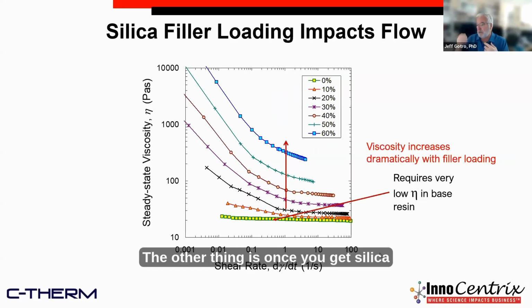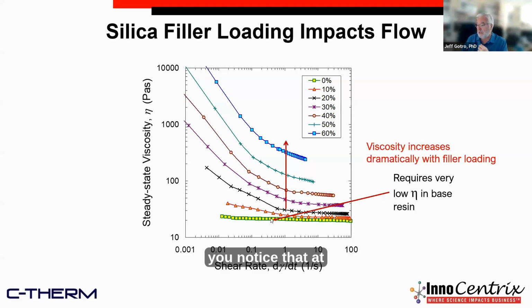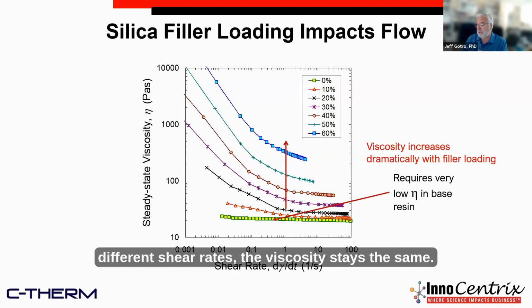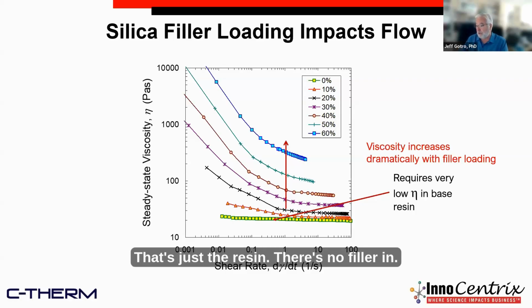The other thing is once you get silica filler in there, let's just say we'll use silica because that is the one that has the lowest, what I call, viscosity penalty. But when you load it up with various levels of silica filler, even then the viscosity goes up dramatically. In this case, the yellow curve at the bottom, you notice that at different shear rates the viscosity stays the same. That's just the resin. There's no filler in it.